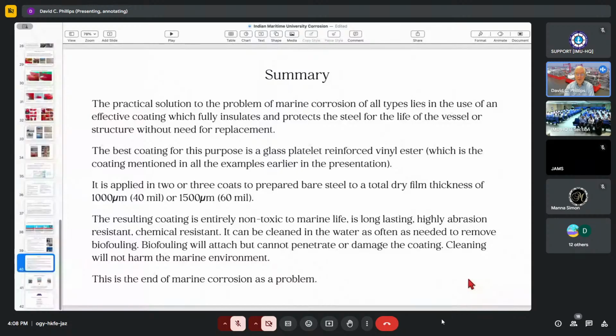The best coating that we found is a vinyl ester reinforced with high aspect ratio, high quality glass platelets. This is the one that's been used in every example I've given you. It needs to be applied to a dry film thickness of 1,000 or more micron thick. The coating, if the ingredients are correctly monitored, is completely non-toxic to marine life. It's inert. It does not put anything into the water.